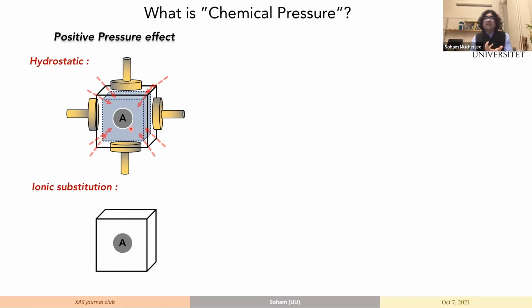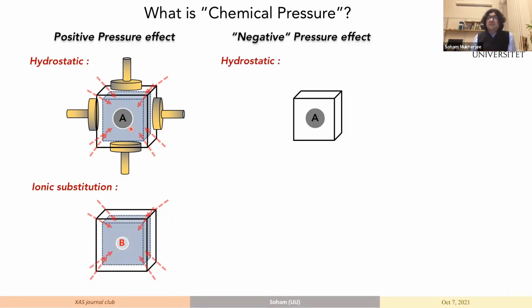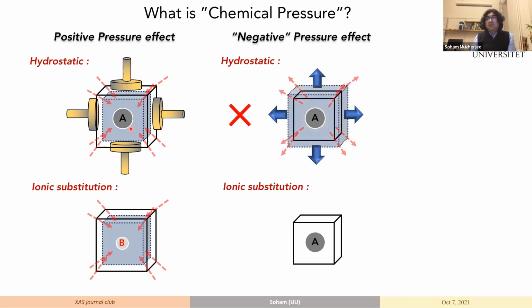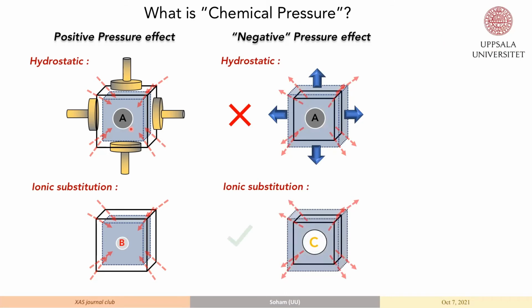But you can do the same thing by replacing a bigger ion with a smaller ion, and this substitution will reduce the cell volume of the system. But think about the other way: when you apply a negative pressure, which is not physically possible when you talk about hydrostatic pressure, you can do the exact same thing by replacing a smaller ion with a bigger ion, so that you increase the unit cell volume. And this immediately became extremely popular because you can now explore the realm of negative pressure.